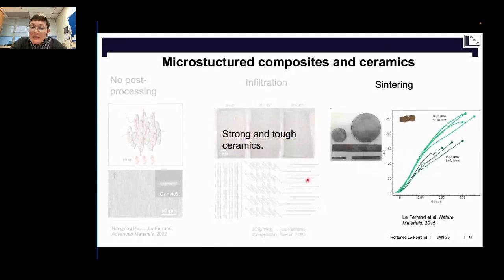Or you can bring it into a furnace, sinter it, and transform it into a ceramic. So these samples here were sintered at high temperature, but also hot pressed. So you apply pressure at the same time as the temperature. And this leads to ceramics that are very difficult to break. So this is what we call these tough nacre-like ceramics.